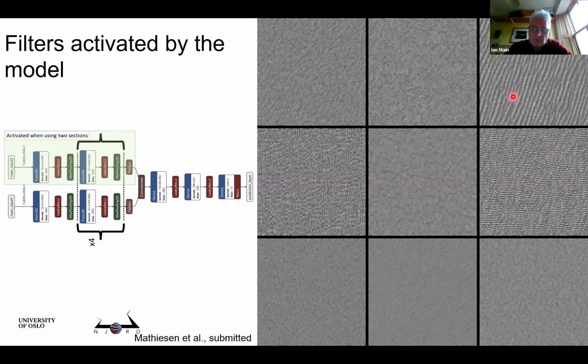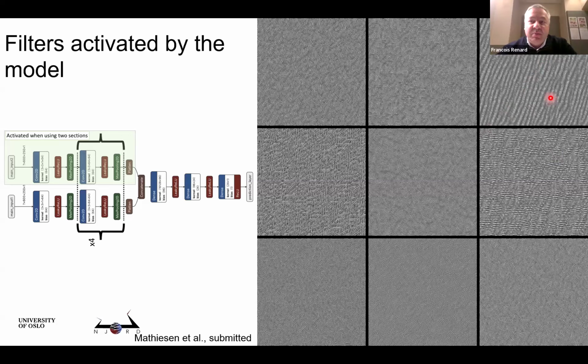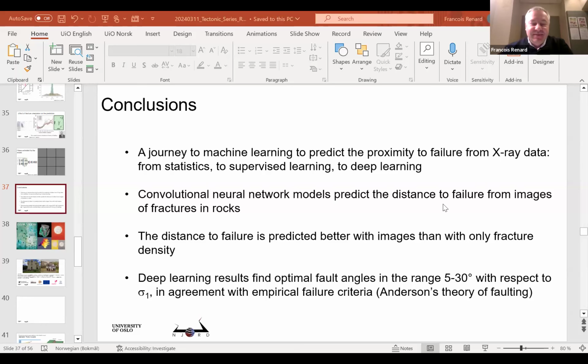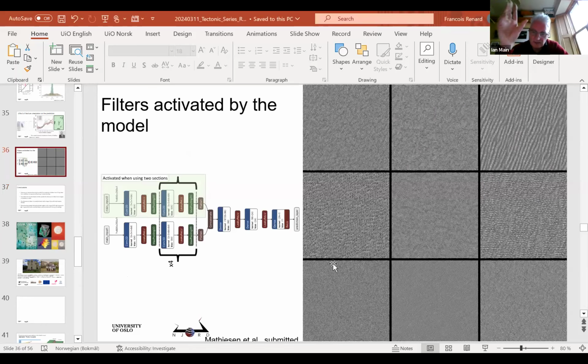And even so, this one was the most obvious analogy to make with the stripes, because there are stripes and they have an angle. But the other ones, you see this one and this one, they have some horizontal. I don't know. Sometimes we say that deep learning is a black box. So we are inside a black box here, and trying to make sense of this black box, I am careful. Yeah, but still, it sort of shows how it's thinking in a strange sort of way. But it's obviously picking up these long-range correlations in the orientation distribution, which is, going back to Georg's question about how fractures link up. They're not growing in that orientation; they're kind of coalescing.